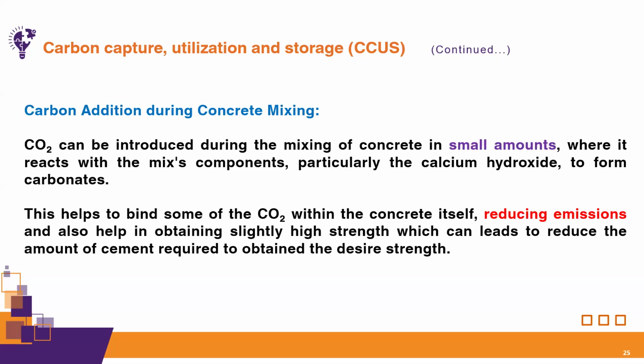So what will happen? This carbon will react with the calcium which is present in the cement, and it will ultimately form again the calcium carbonate. So this method will help to bind some of the carbon within the concrete itself, and it will also reduce the emission because you are utilizing the carbon, and it will also give you slightly higher strength.